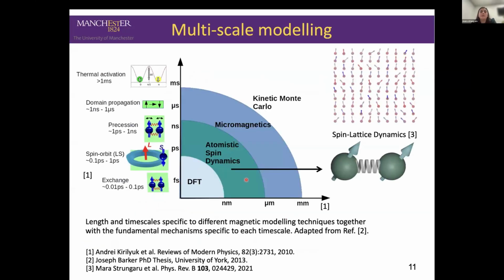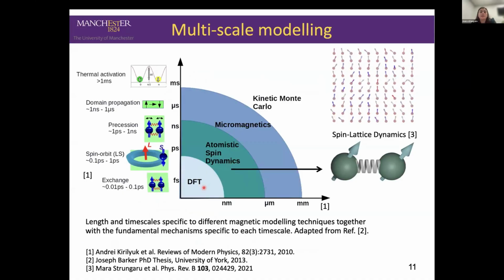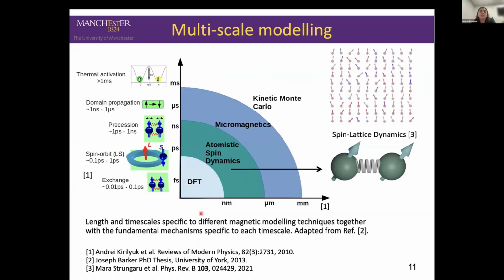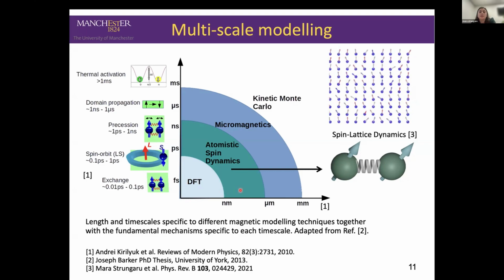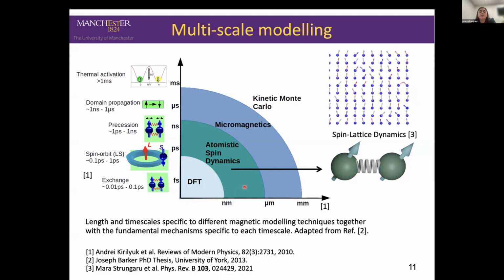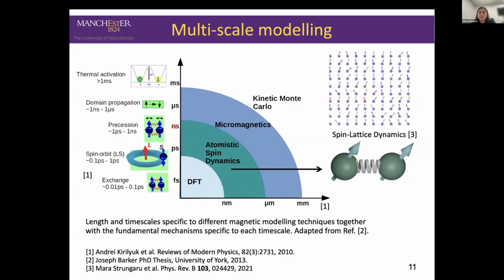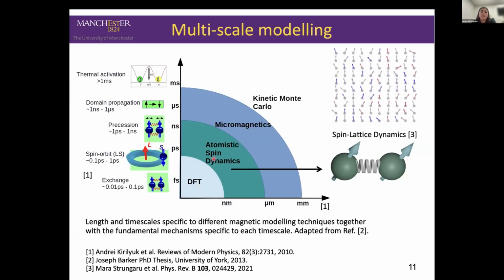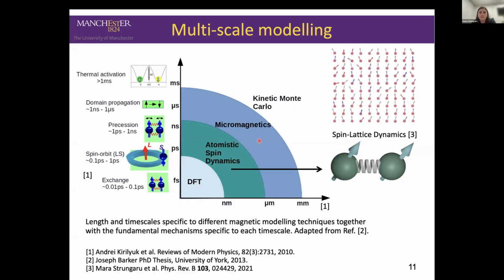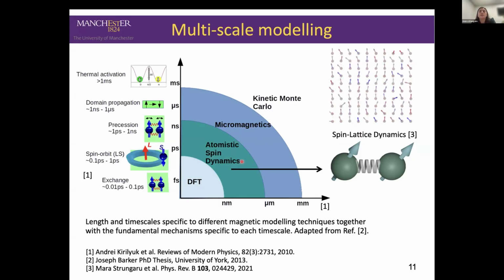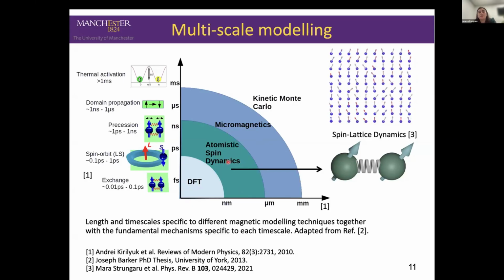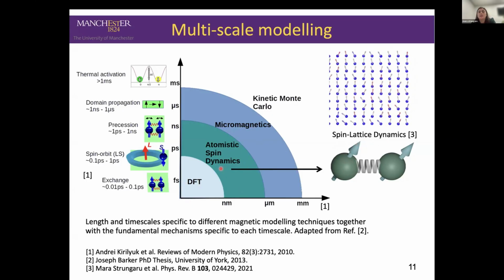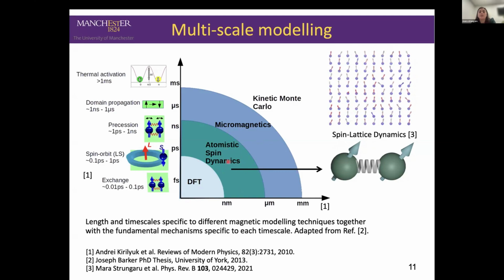Essentially, atomistic spin dynamics is a multi-scale model, since for the parameterization of exchange, we can use first-principles calculations in the form of density functional theory. We are able to access length scales of nanometers to micrometers system sizes, and picoseconds to nanoseconds time scales. And we can use the output from atomistic spin dynamics in micromagnetic modeling. Until very recently, atomistic spin dynamics has considered a fixed lattice. However, by coupling to molecular dynamics, you can build what's called the spin lattice dynamics framework and also access the dynamics corresponding to lattice vibrations and phonons.